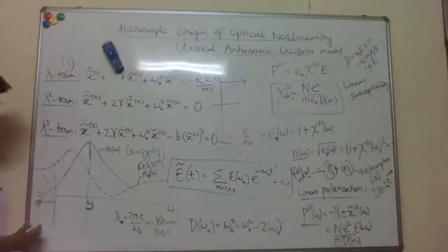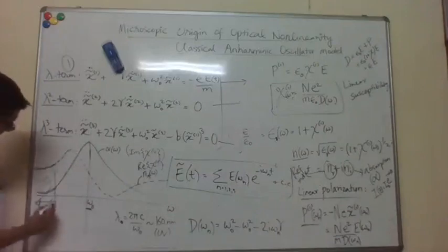Okay, so basically, you want to operate mostly here, at frequencies which are much smaller than my resonance frequency, such that my alpha is basically 0. In that regime, you can see that the refractive index becomes almost constant. For glass, we typically operate at wavelengths greater than, let's say, 500 nanometer.